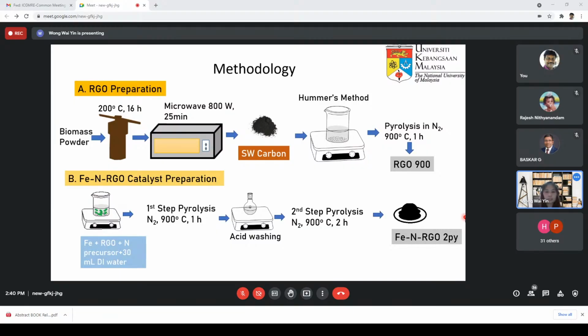So far, for the synthesis of reduced graphene oxide from biomass, they normally use a base activation method, using KOH. In this one, we are looking at other options, where there have not been any attempts at using Hummers' method, which is normally used to prepare reduced graphene oxide from graphite. There have not been any attempts on biomass yet. So we are attempting this method. The biomass was first carbonized using a hydrothermal method and then microwaved to produce a carbon powder.